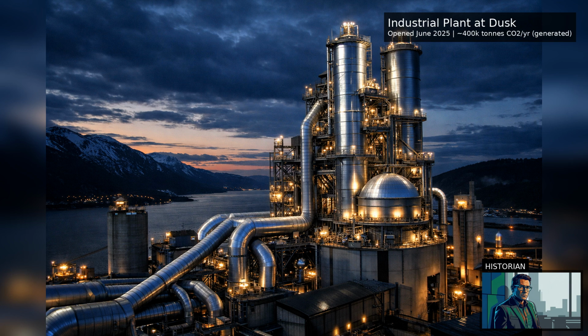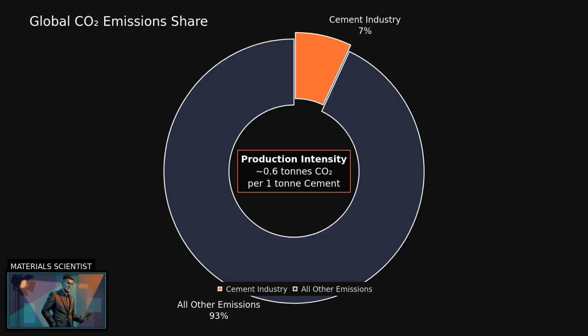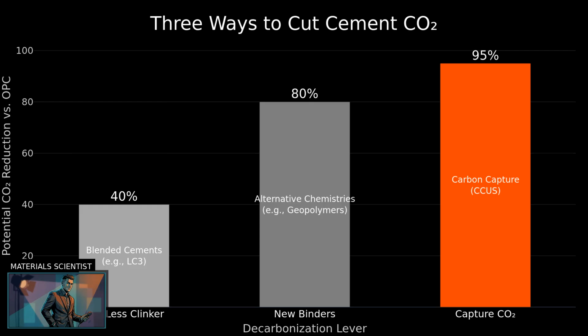Seeing a modern plant on screen makes the contrast feel enormous. The scale is enormous. Cement is responsible for about 7% of global CO2 emissions. And, on average, making a ton of cement releases on the order of 0.6 of a ton of CO2, mostly because of clinker. So we can clean up the heat, but we can't electrify away the limestone splitting. Solar doesn't stop that CO2 from forming. Precisely. Efficiency helps, but chemistry sets the floor.